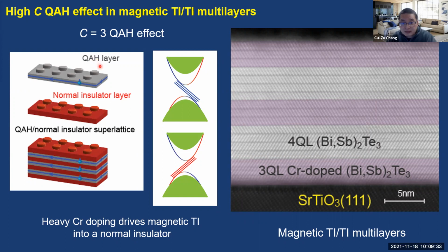So in our experiment, the idea is like this. We heavily doped chromium in the magnetic TI layers. Heavy chromium doping can reduce the spin-orbit coupling, because chromium is much lighter than the bismuth or antimony in the topological insulator films. If we dope a lot of chromium, we could reduce the spin-orbit coupling and drive it to the normal insulator regime. And in the undoped TI layer regime, we could realize the C equals 1 quantum anomalous Hall layers. Therefore, we grew very heavily chromium-doped TI and pure undoped TI in multilayer structures.